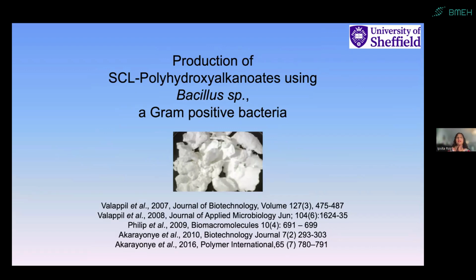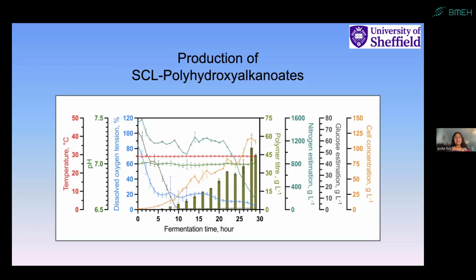In gram-positive bacteria, we do not have lipopolysaccharides, which are known immunogens, and therefore the polymer that you produce would have no risk of containing any lipopolysaccharides, and would be excellent for medical applications. This was my reason for focusing on Bacillus species, and I mainly produce short chain length PHAs using this species. This is a typical temporal profile of the polymer production.